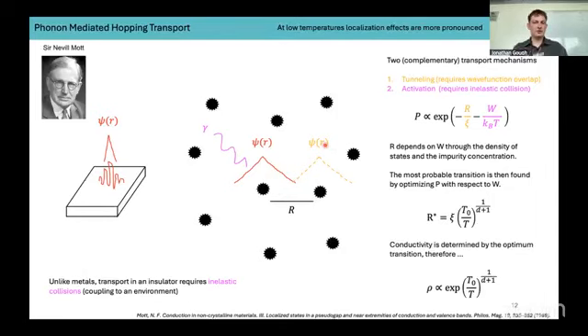I should mention also that these two mechanisms work in tandem with each other. You can't really have one without the other for a localized system. So what Professor Mott did was essentially express R in terms of W through things like the density of states and the impurity concentration, optimize P with respect to W, and by doing so, you return this very famous result where the typical hopping length, R star, depends on temperature.